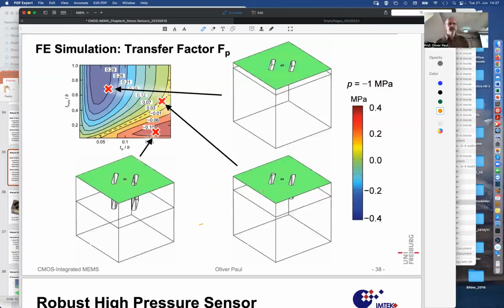And so that's why ultimately this design was adopted with 100 micron of silicon on 1 millimeter or so of glass, because you can easily thin down silicon to the level of 100 micrometers. And then glass bodies of 1 cubic millimeter can be bought, or wafers can be bought and they can be diced easily. And so that's what ultimately Mark's choice was. Also, this has the highest sensitivity. That is the reason for the choice.